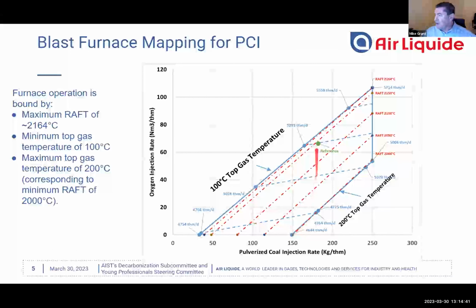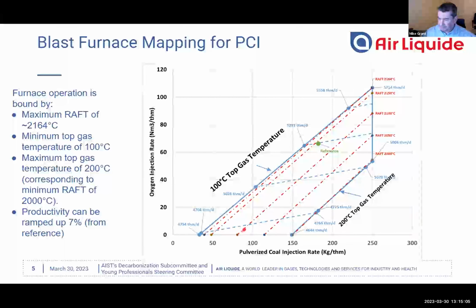So as long as we operate within this range here, we can operate the blast furnace fairly smoothly. If we can achieve our maximum coal injection, which is defined here as 250 kilograms, this will allow us, combined with oxygen, to increase the productivity by up to 7%.